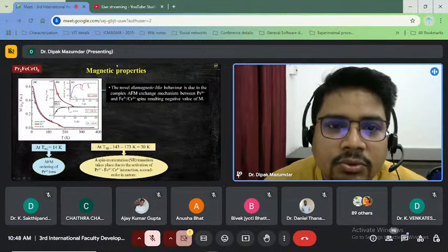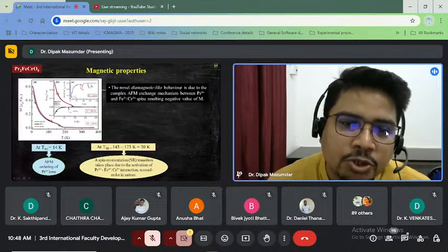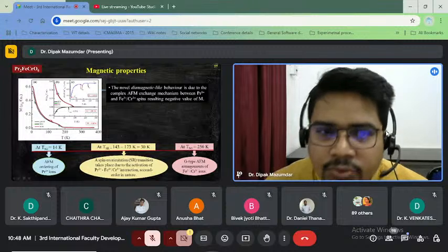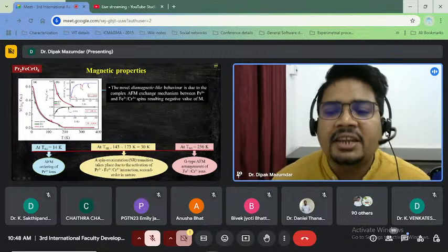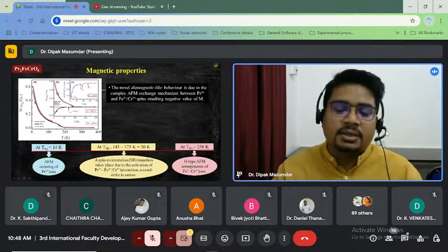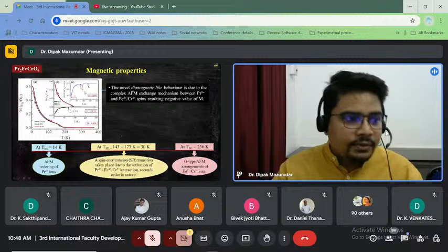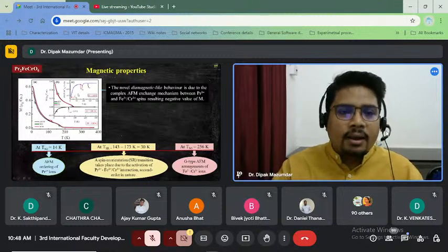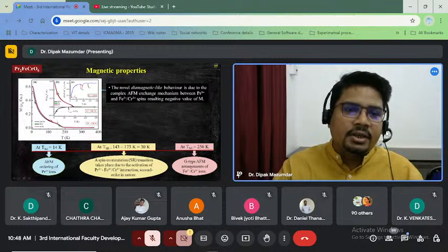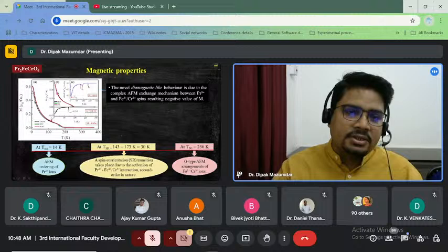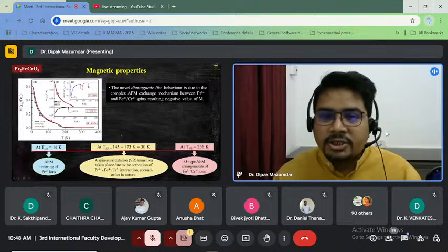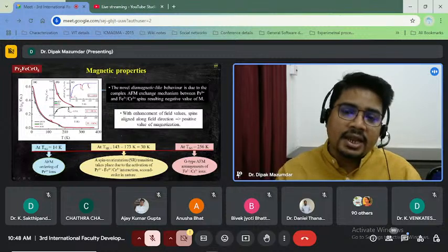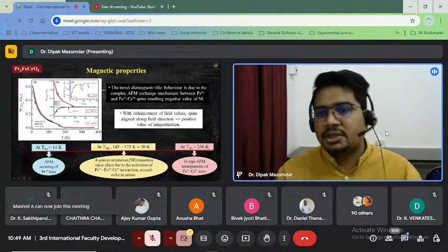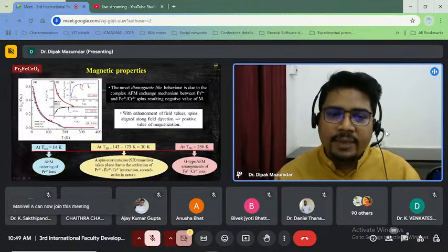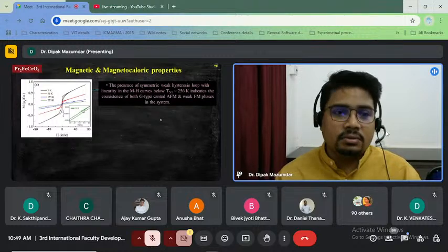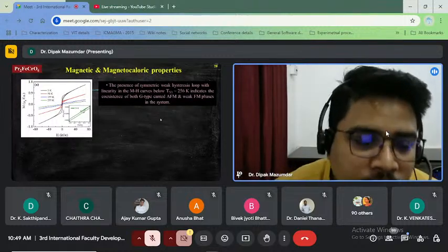And the last transition, which we can observe by zooming into this portion, is at TN1 around 256 Kelvin. Here, the G-type antiferromagnetic arrangement of iron and chromium ions takes place. So basically, here we have observed three types of transitions in the low field region. But when you apply a high field, this negative magnetization disappears, and the system behaves as completely antiferromagnetic in nature. So is there any conclusion? Yes, with enhancement of the field value, spins align along the field direction, resulting in a positive value of magnetization. And after that we calculated the isothermal magnetization data.